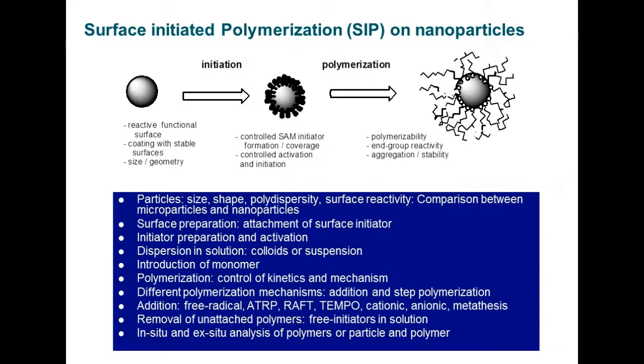So we can take, let's say, a clay particle or a silica nanoparticle, and then populate the surface with surface initiator such that we can grow the polymer as a brush in a core-shell geometry, thereby changing the steric stability of the colloidal particle with respect to solution. So we've done this effectively to functionalize things like clay or silica in order to prepare nanocomposite materials with unique